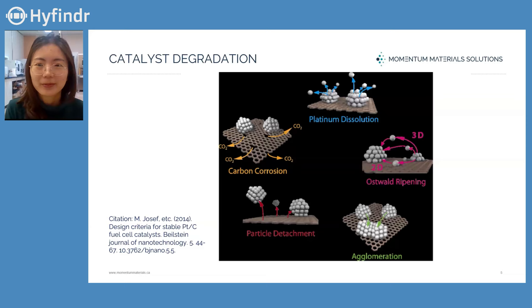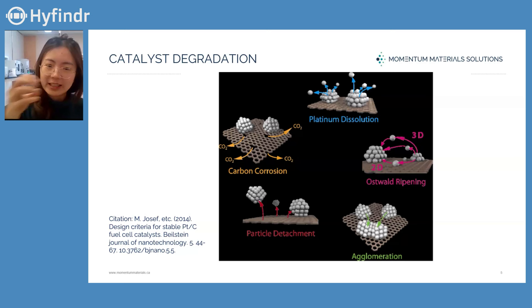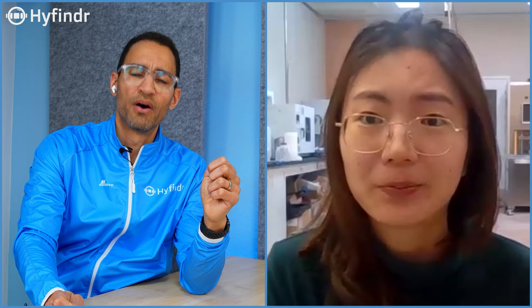So both the support material and the catalyst face wear and tear — what is the exact physical thing that happens? When the platinum nanoparticles are detached from the support materials, they mainly lose their activity because they're no longer electrically connected with the whole fuel cell. And when platinum agglomerates, it loses its surface area, which means it's also losing its activity — so it's either detached or clogged.